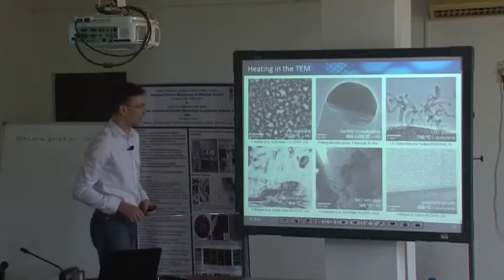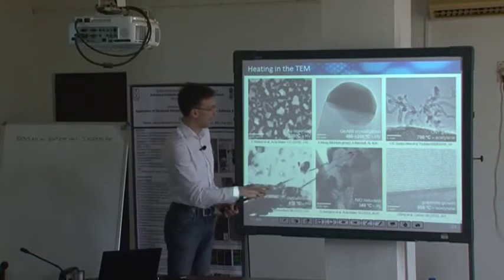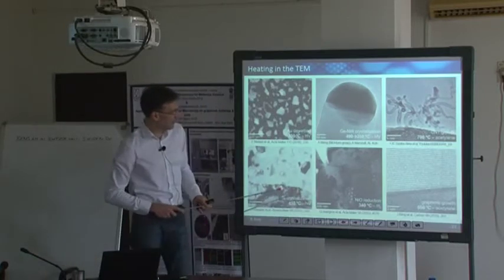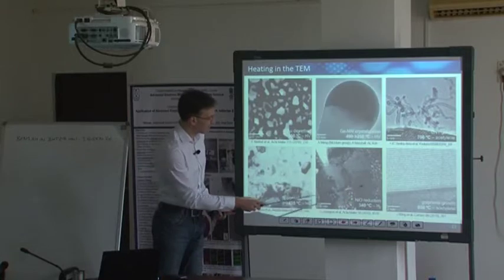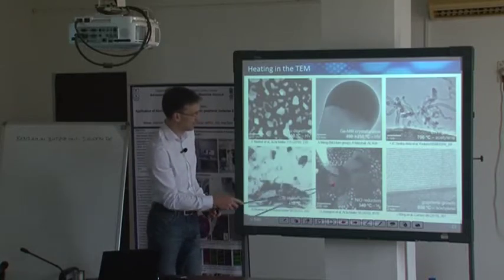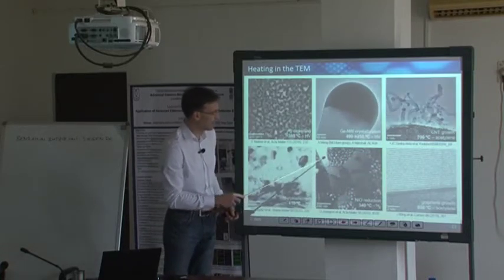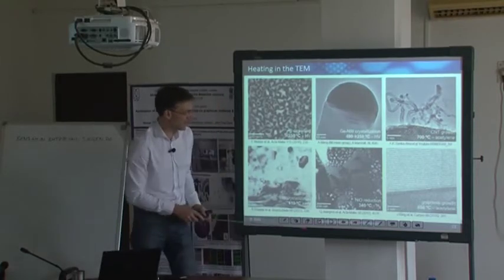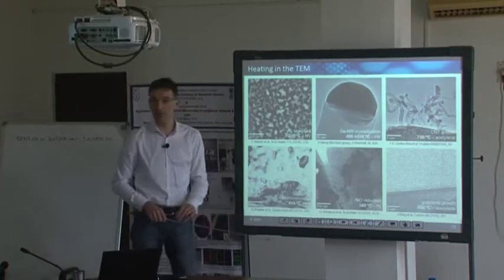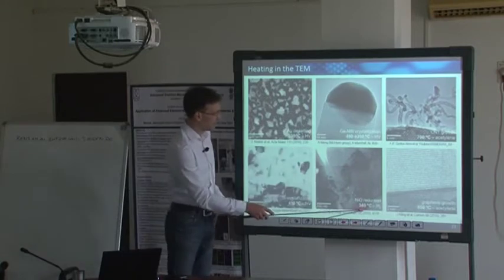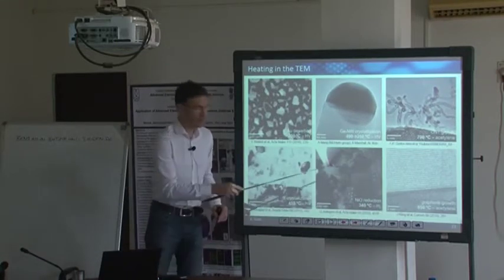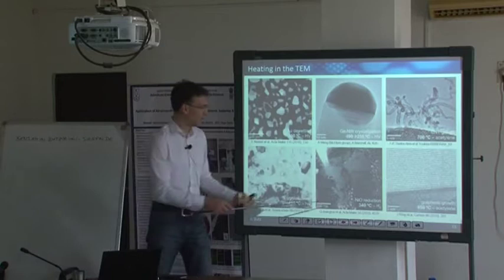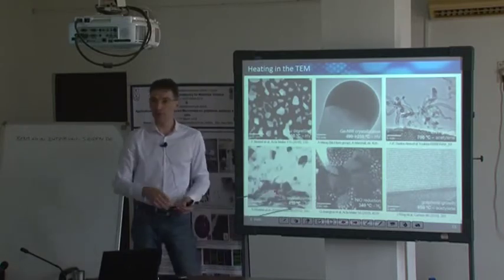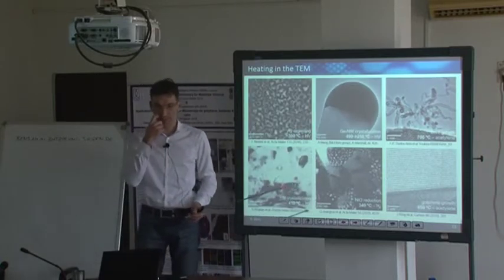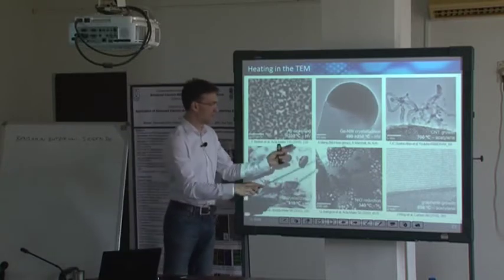This is the reduction of a nickel zirconium oxide anode of a fuel cell, where you see some nickel grains, and in between there are some zirconium oxide grains. The nickel gets reduced here. This is done in a hydrogen environment in a microscope at 340 degrees, and by that, people are able to follow the reduction, and if you cycle and operate a fuel cell, the question is always whether those materials fail or not.